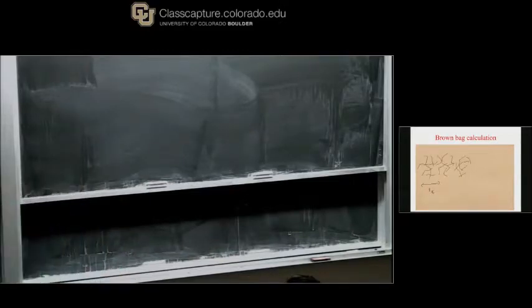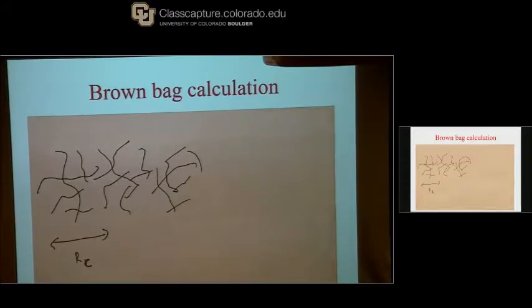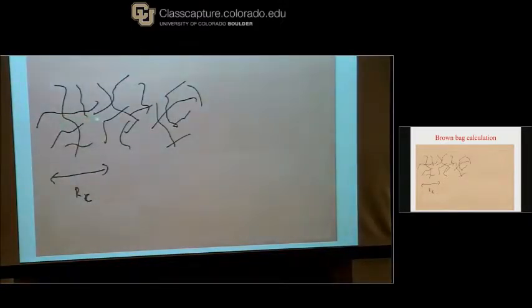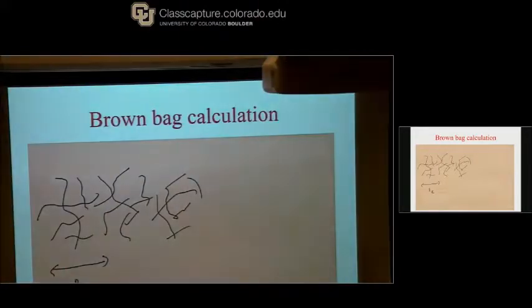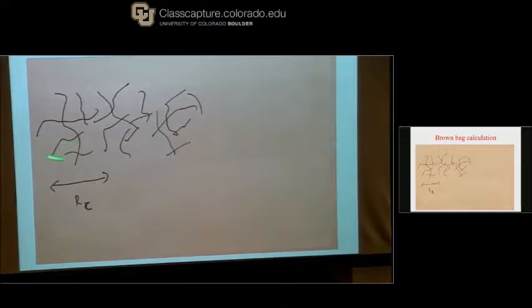So what's going to happen, I've tried to draw that here. You're going to form clusters. As they get larger and larger, you need less and less material to get more and more volume. This is meant to represent 3 different clusters. Eventually they're so dilute that they're essentially filling all of space, and they'll gel. So they'll be fractal up to some length scale, which I called R sub c, a critical crossover length scale. Above that length scale, they're uniform.